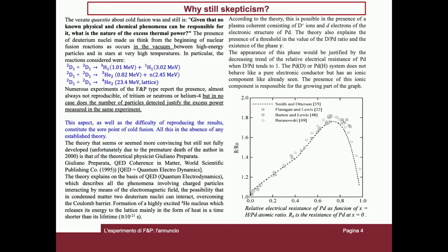The theory that seems or seemed more convincing, but still not fully developed, unfortunately due to the premature death of the author in 2000, is that of the theoretical physicist Giuliano Preparata. The theory explains, on the basis of a quantum electrodynamics, which describes all the phenomena involving charged particles interacting by means of the electromagnetic field, the possibility that in the condensed matter two deuterium nuclei can interact by overcoming the Coulomb barrier. Formation of a highly excited helium-4 nucleus, which releases its energy to the lattice mainly in the form of heat, in a time less than its lifetime, which is about 10 to the minus 21 seconds.